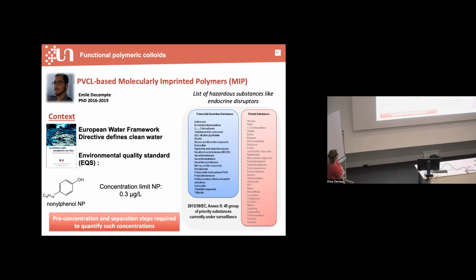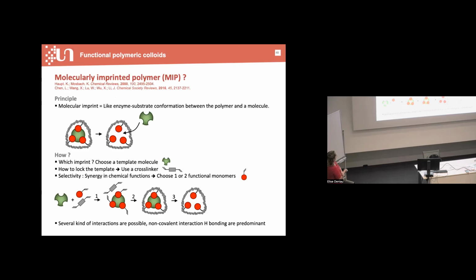And then we got the idea to use such a vinyl caprolactam microgel to develop molecularly imprinted polymer colloids for the pre-concentration and separation of nonyl phenol, which is a micropollutant of water and classified as an endocrine disruptor. So molecularly imprinted polymers, MIPs, are a network with a cavity which is selective to a template molecule, because the network is formed in the presence of the template molecule, represented here in green, which forms selective interactions with the monomer units, mainly by H-bonding interaction. And after removing the template molecule, you form a cavity which is selective for this molecule.